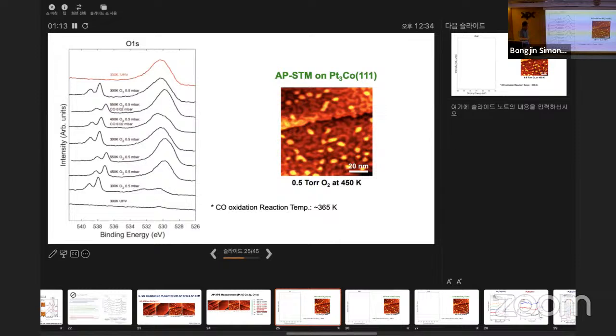In other words, what we are seeing here at a temperature of about 450 and pressures of 500 millitorr is something we are seeing somewhere here. And this is a big blob of this oxygen 1s. It's reflecting the chemical state of all this. There is no single state. Actually, there are many states of the oxygen, where some of them are getting reduced, and some of them remain strong. And this is due to the reaction with the CO.